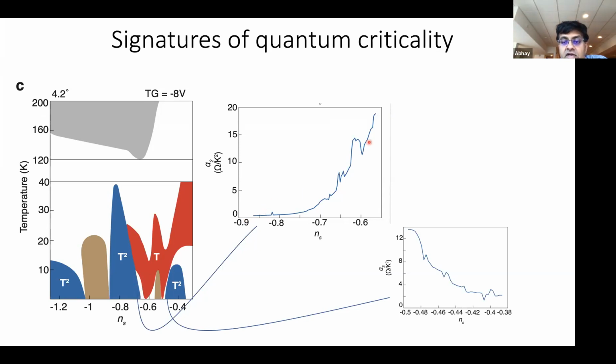And I had my student, and he doesn't like to make nice plots, so I have to force him. So the nice plot hasn't emerged yet, but this shows you real raw data of what that coefficient of the T-squared behavior is. And you can really see that it enhances by a factor of more than something like 30 or 40 as you approach this quantum critical point. And similarly, as you approach it from the other side, as you come from here to here, it also enhances by similarly 20 or of that order.